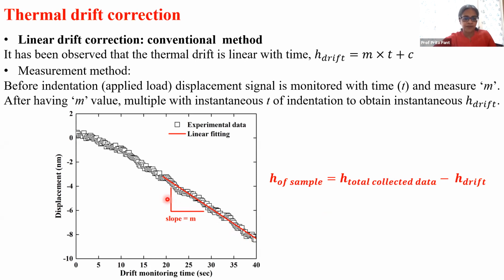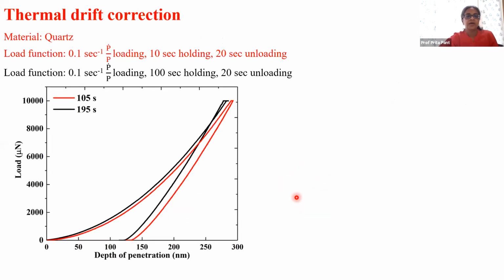So at the beginning of every experiment, this is automatically done. Displacement is measured as a function of time for 40 seconds, and to the last 20 seconds of data, a straight line is fit, m into t plus c kind of a straight line. This m is calculated. And then if you know the time of your experiment, you know the slope, you calculate displacement due to drift, you subtract it from the total data, and you know the displacement into the sample, the intended displacement. So that's fairly straightforward.